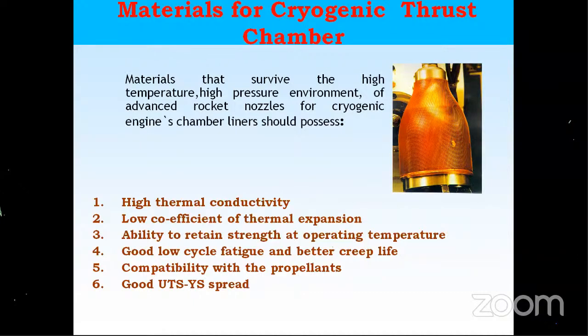So the importance of the copper alloy is that this is a channel wall. There will be an outer cover on this, and it will be brazed. Through the channels liquid hydrogen will be flowing, and the inside temperature is as high as about 3,500 K. And the copper temperature, because of the liquid hydrogen, it's regenerative cooling, will be as high as about 600 degrees centigrade. This is the entire world, even NASA or ESA or Russia, everywhere the same thing is used.